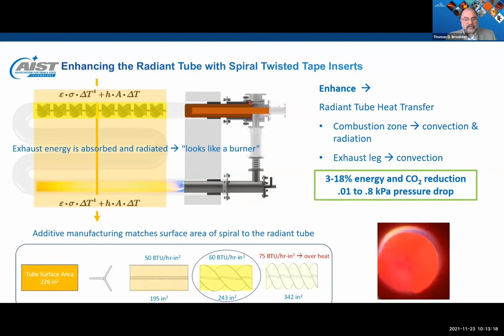The use of a spiral twisted tape insert provides an effective means when combined with additive manufacturing to make a device that absorbs exhaust energy and re-radiates similar to a flame. Interestingly, we find that a ratio of the surface area of the tube to that of the twisted tape being approximately 1 gives the ideal balance of radiation and convection in the exhaust leg. Additive manufacturing, as compared to slip casting or injection molding, allows the twist rate to be easily modified and optimized for a given radiant tube.